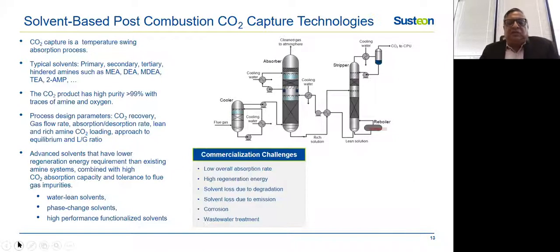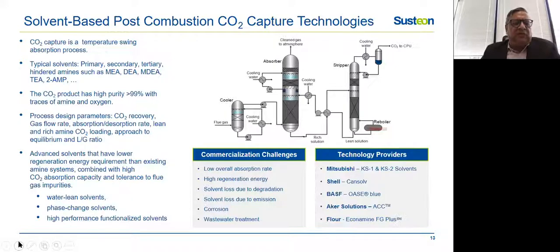If you look at the commercialization challenges for these materials, one is the low overall absorption rate. If you can increase the absorption rate, we can reduce the column height and the capital cost. High regeneration energy is one of the most important challenges, because this directly relates to the total capture cost. Then there are loss of solvent due to degradation, solvent loss due to emissions, corrosion, and wastewater treatment. Some of the technology providers which supply commercial technology for this application are Mitsubishi, Shell, BASF, Aker Solutions, Fluor, and there are other new technologies which are coming up in the market.